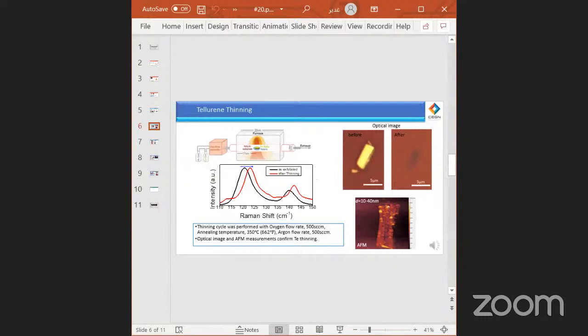After investigating Te thicknesses using AFM and Raman spectra, we move forward to control the flake thicknesses by applying annealing to all the Te flakes under oxygen gas at 350 Celsius, where a blue shift is observed in all Raman modes after thinning. And from the left optical image, we can see the comparison between Te flakes before and after thinning. The thickness dropped from a few hundred nanometers to a few layers, where the color of the flakes also shifted from bright yellow to gray and light blue.